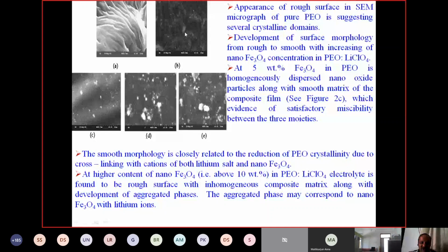So when you increase up to a certain content of Fe3O4, the mechanical strength is high, but when you increase to a further higher concentration of Fe3O4, it again damages the film. So whatever it may be, it accommodates only up to a particular composition. Even when we studied polymer electrolyte materials, up to a particular composition, it accommodates the salt perfectly, and it also increases the transfer property.